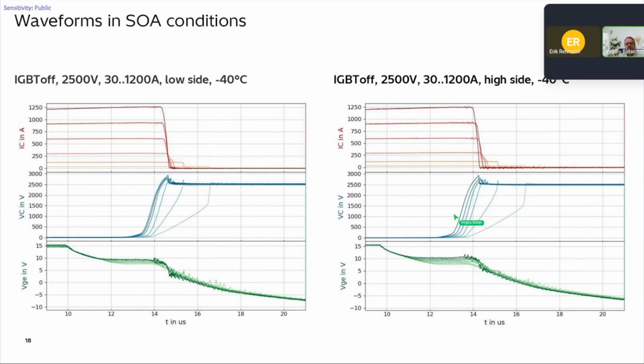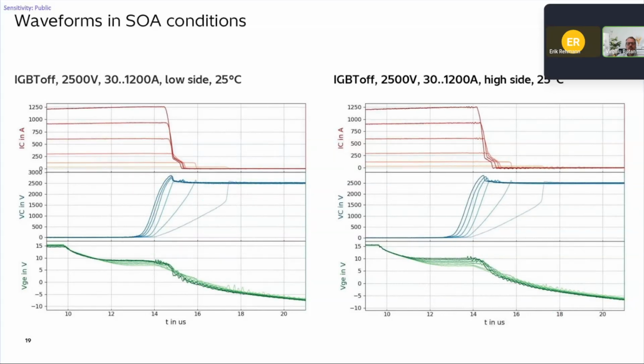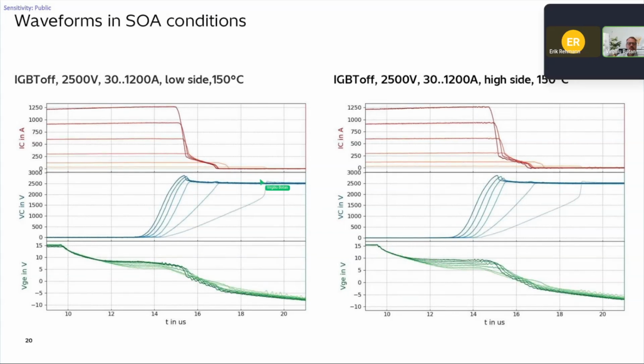A couple of waveforms on the SOA, going down to minus 40 degrees. We can see from very low currents up to SOA currents at minus 40 degrees, no problem. Then room temperature, quite a soft behavior even at cold, and here also 150 degrees, a current series from 0 to SOA current. So all in all, very robust behavior, soft for all applications, even applications that might have higher stray inductance.